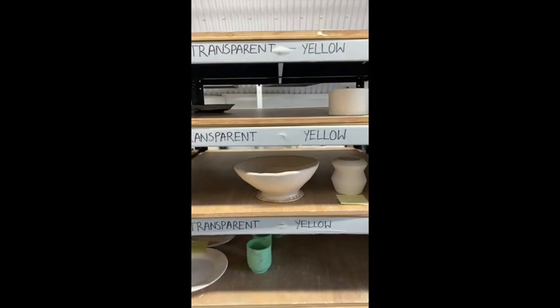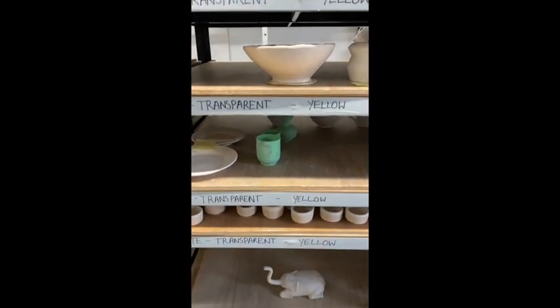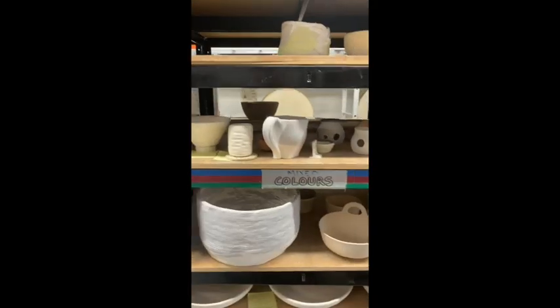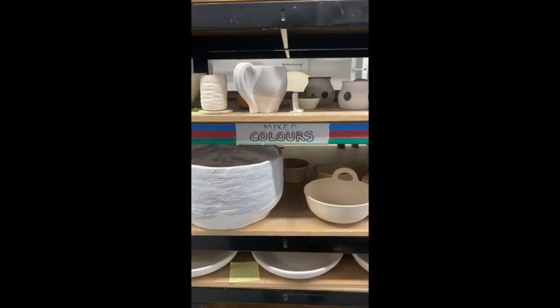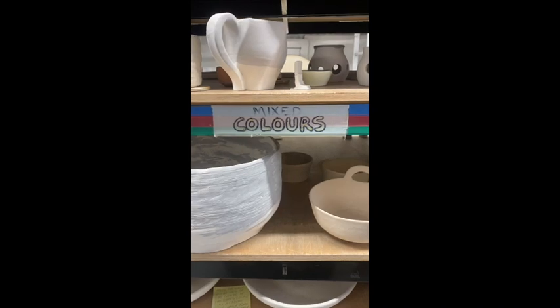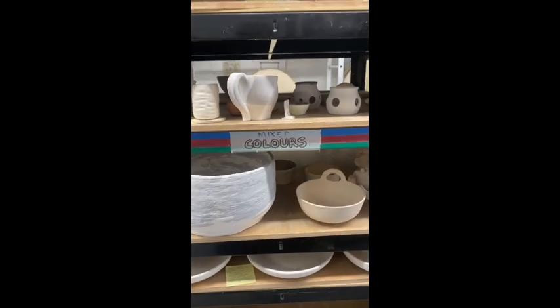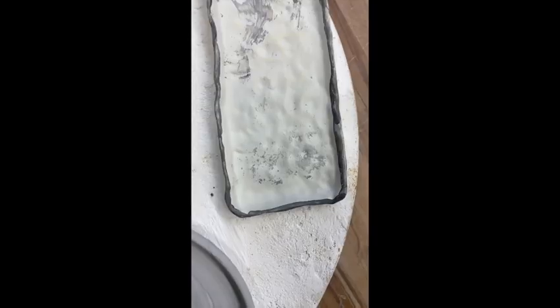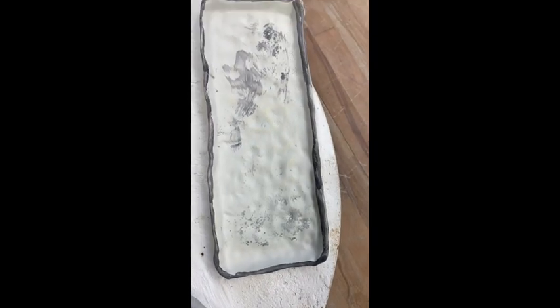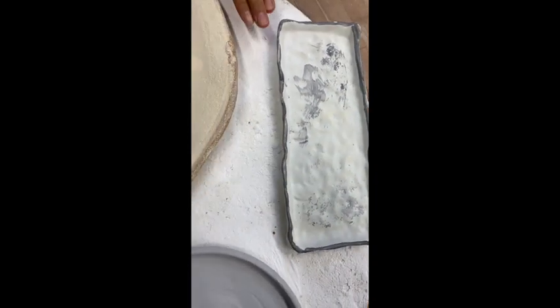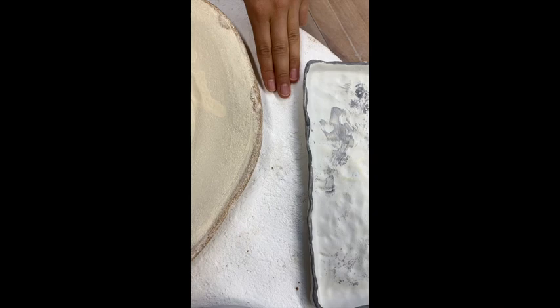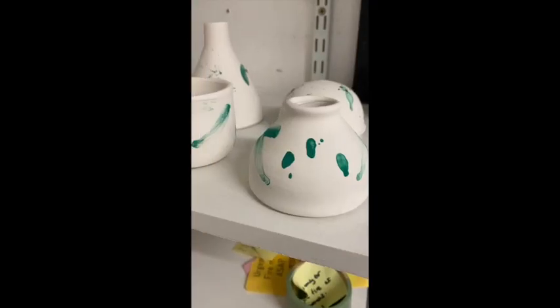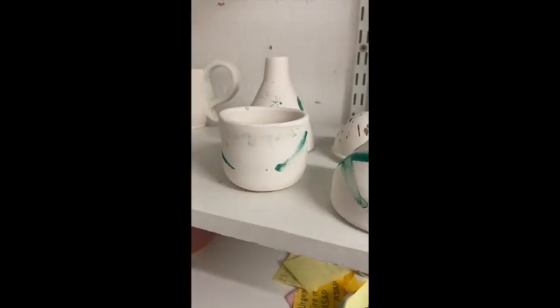Flashing is when glazes jump from one pot to another during the firing. If possible, we only put dark colours on the bottom shelves in Bellenden Road. Please be aware of oxides. Oxides tend to flash more frequently than glazes, so we like to give 3 fingers width between any pieces that have oxides on the surface.